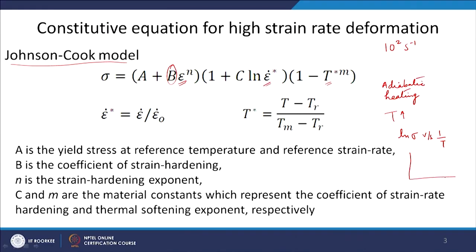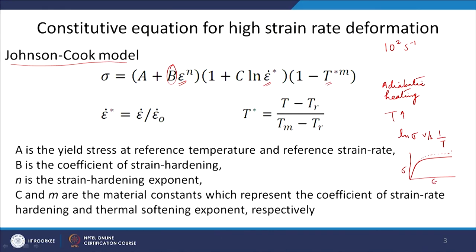That means, if this is my stress-strain curve with the stress which I have measured, after the compensation the stress will obviously be higher than that, because the temperature should have been lower than that. So this type of temperature compensation in stress you have to give when you are doing a high strain rate deformation. I forgot to bring it out earlier, so I am doing it now.